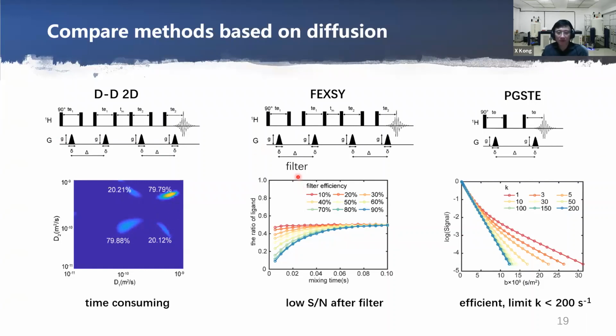The second is a filtered exchange experiment, also called FEXSY. The FEXSY uses exactly the same pulse sequence, but uses the first block as a filter to filter out part of the signal to create a non-equilibrium magnetization. The FEXSY can be much more efficient than the 2D, but the filter reduces the signal intensity dramatically, and it still needs multiple mixing times to get an exchange rate.